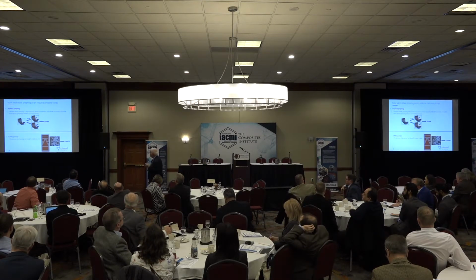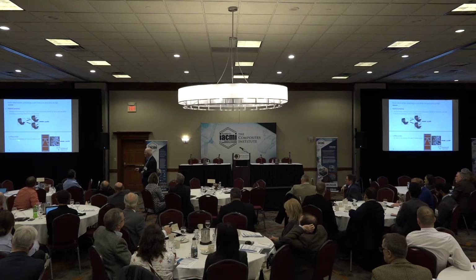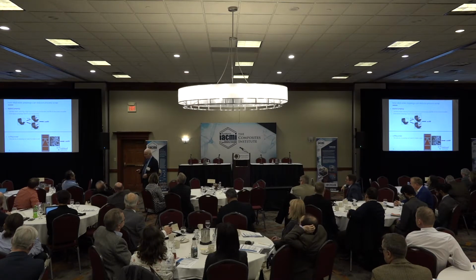It's possible because the chemistries are very similar and the molding conditions are very similar. The time, the temperature, the pressure, the catalysts. So it becomes possible to co-mold material even when it's in scrap form. And just to summarize how vinyl esters can reduce processed scrap, I've made a distinction here between expired prepreg and cutting scrap. Because with epoxies, what you'll see is that they will expire as a function of time, or they can make out of spec material, and all that needs to go to a landfill.